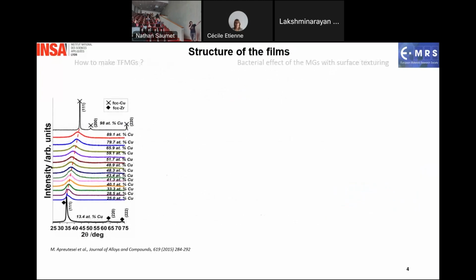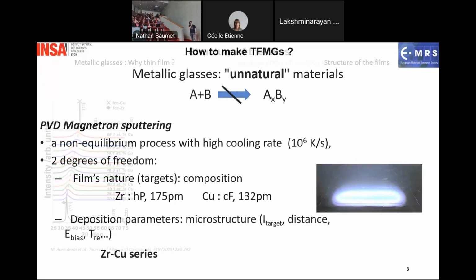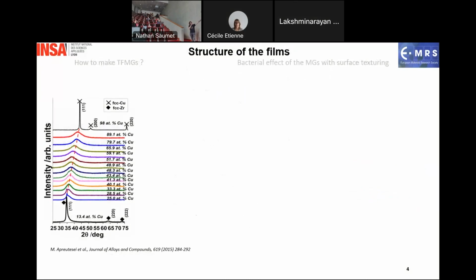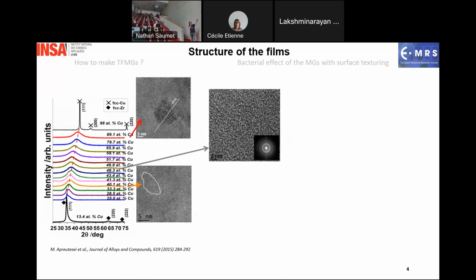And we work here on zirconium copper metallic glasses. Measurements on metallic glasses with copper composition from 25 to nearly 100% show that from 30 to 90% of copper we have amorphous thin layers, but with TEM images we see little crystallites. The absence of crystallites, the perfect amorphous phase, is only found near the 50-50 composition. Here are the TEM image and the diffraction pattern of the image.